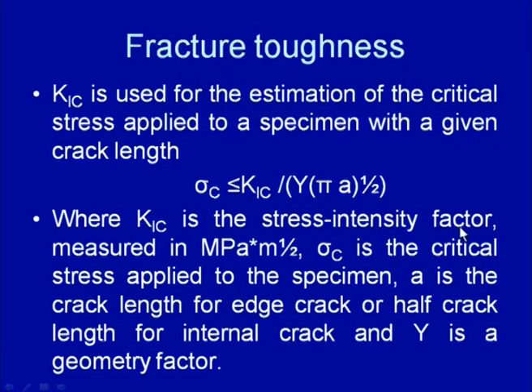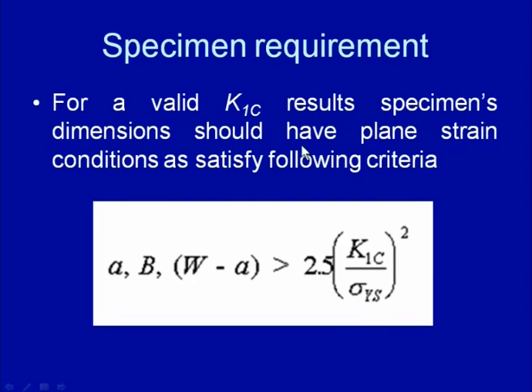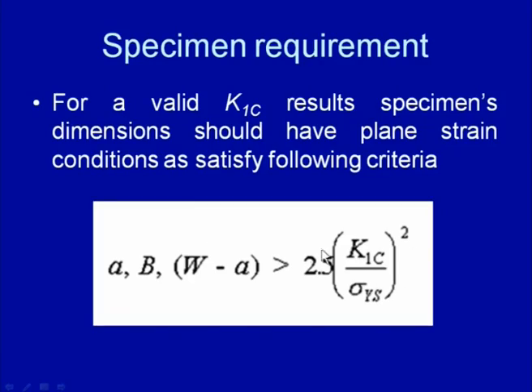So, here K1C is a critical stress intensity factor measured in MPa square root of meter, and sigma c is the critical stress applied to the specimen. A is the crack length for the edge crack and half crack length for the internal crack, and Y is the geometric factor. For valid K1C results, the specimen dimensions should have plane strain conditions and satisfy the following criteria: a, B, that is the thickness of the plate, and W minus A, should be greater than 2.5 times (K1C divided by the yield strength of the material sigma ys) whole square.